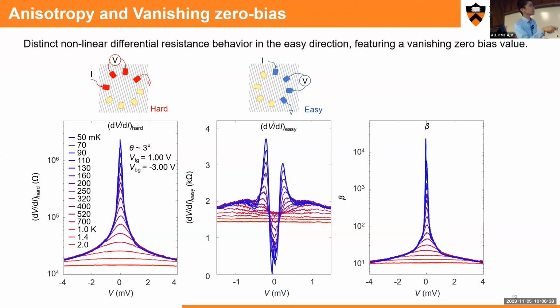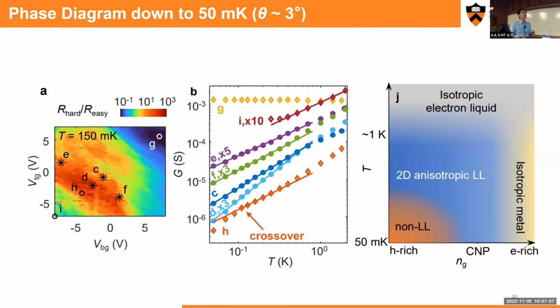If you check the anisotropy, which is this number over this number, you can see that the anisotropy in this 3 degree device can go even higher at very low temperature, say 50 millikelvin in this situation. You can go to 10 to the 4th. And actually the dip here can keep vanishing. If you have a higher quality device, it can keep vanishing going towards 0. And this is a very distinct behavior in this kind of system.